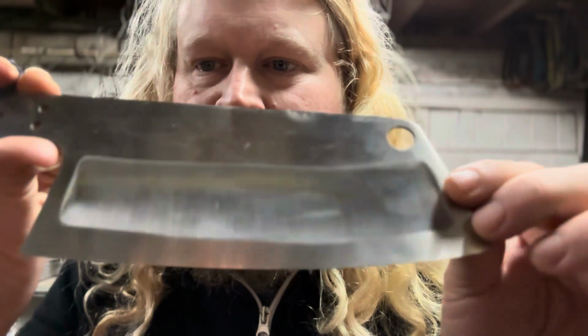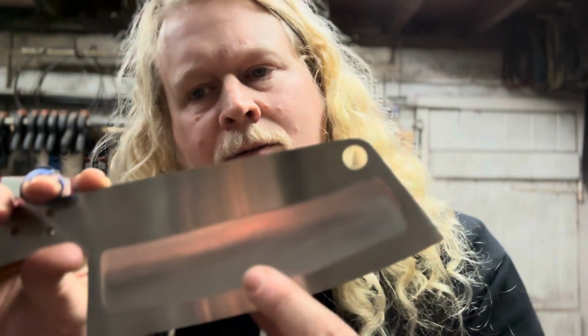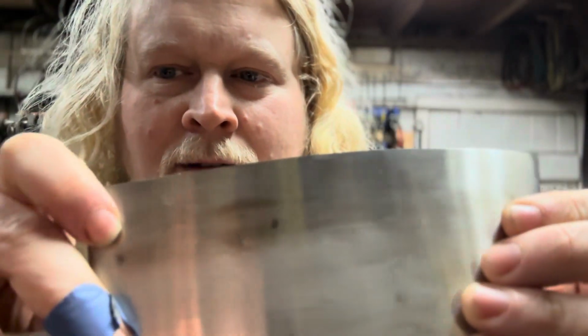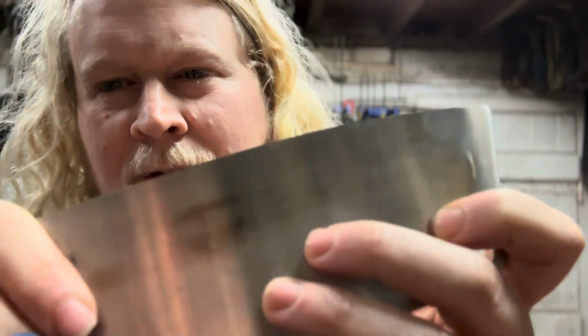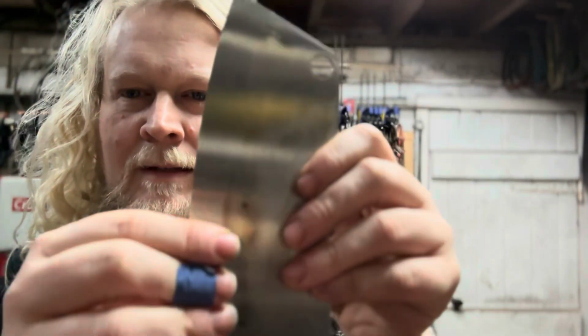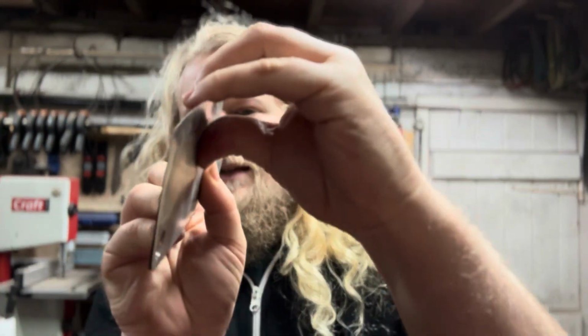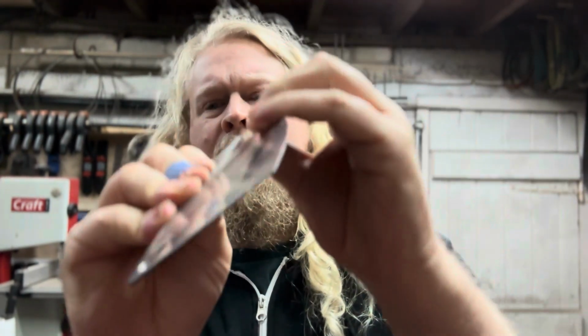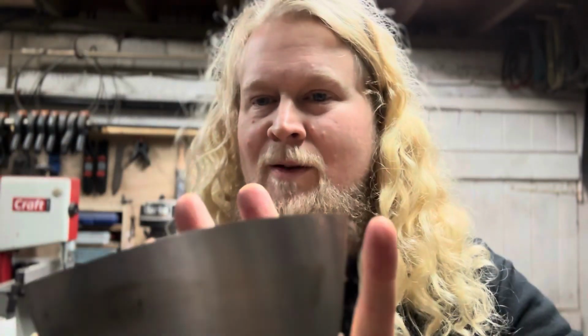So I did a C grind on this one. I was starting with thinner stock, and I tried it quite low. You can see it's still a mess because I gave up, but I went right through the knife in 2 places, one in the middle there. You can see where it's burnt, the temper's gone, and surprisingly the blade doesn't snap, but that's not what you want. And that's quite devastating. That knife was heat treated, I'd fully ground all the bevels, and it was pretty much ready to go once I put the handle on.